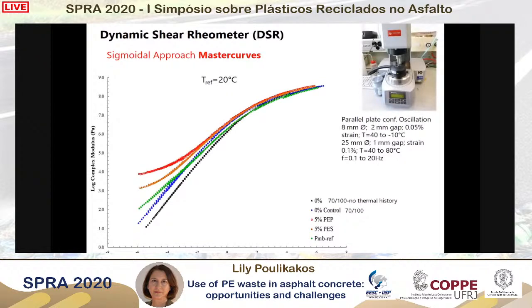Now, I think that the dynamic shear rheometer and the results we get from this device are a very powerful tool in our field. Here we can see the modulus of these materials as a function of frequency. We have tested the material at various temperatures and frequencies and then produced these master curves. First of all, you see in black the base binder 70/100 with no thermal history. Then we have the blue, which is the same 70/100 that went through the same preparation procedure as the other material, so it went through some thermal aging. You see the modulus has increased. Then we have the polymer modified binder in green, and the two red and orange curves are for the plastic blends.